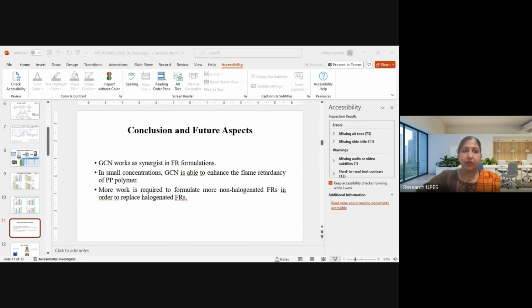So here we can conclude that GCN has been used successfully as the synergist in the regular FR formulations. Another thing, we had done all the tests in polypropylene. Polypropylene uses piperazine pyrophosphate in an amount around 30%, whereas when we use magnesium dihydroxide in polypropylene, it is used at 60%. But when we are using GCN, it is used only at around 15%, and we are getting better efficiency.